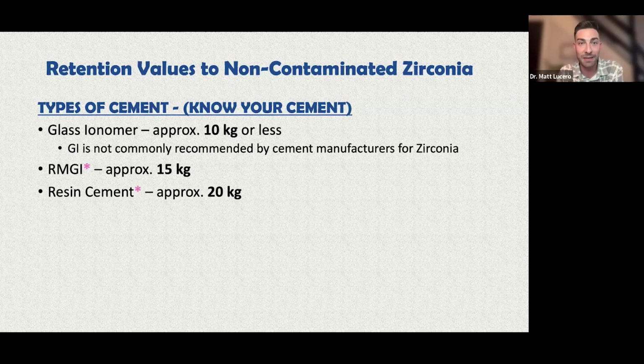Downside to a resin cement is you have to keep things really, really well isolated because we have to etch and bond and go through the whole bonding protocol. And with our patients, that's usually not the easiest option for us. And then there's Biosem, which we'll go into a little bit more detail on. Biosem is a bioactive cement, similar to RMGI, very, very similar in handling characteristics. The biggest benefit to Biosem is that it's a dual cure. So you'll see in the case we do here later, I tack cure those crowns in place, clean up the excess, which is a little bit rubbery, so it's super easy to clean up, and then we do a final cure, and then we're done.